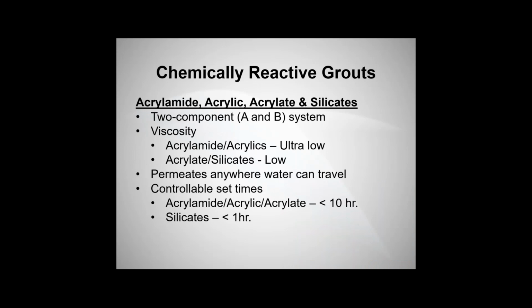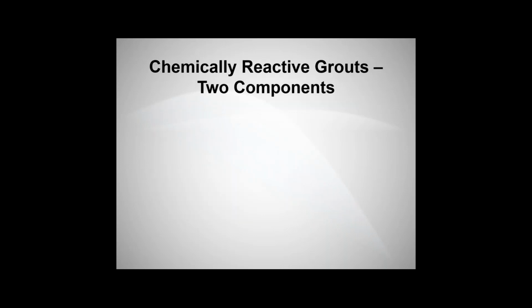Jumping into the chemically reactive grouts, they comprise, again, the acrylamides, the acrylics, acrylates, and silicates. They are a two-component A and B system. The viscosities are generally very, very low, ultra low for the acrylamide and acrylics, low for the acrylates and silicates. Basically, they can permeate anywhere water can travel, and they have controllable set times. The acrylamides and acrylates up to 10 hours. I've actually seen them go longer than that. Silicates about an hour.